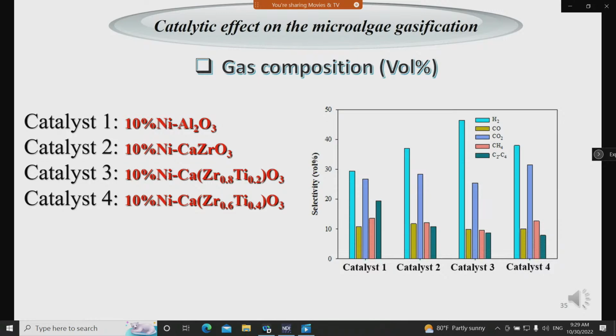However, by further increasing the titanium into perovskite structure, the amount of oxygen mobility will be excessively enhanced, which stimulated the reaction toward CO2 production, so decreasing the hydrogen selectivity.